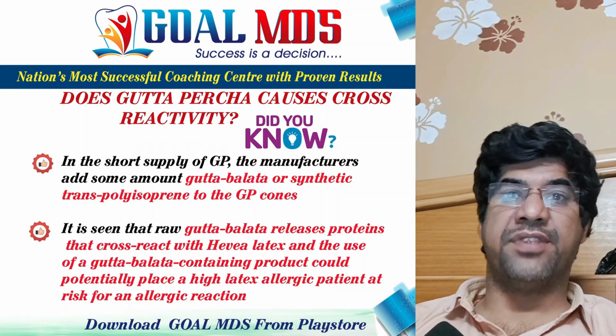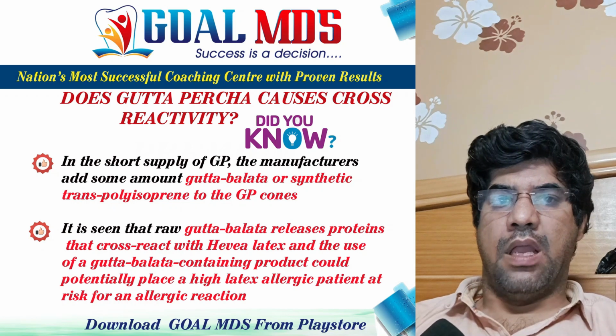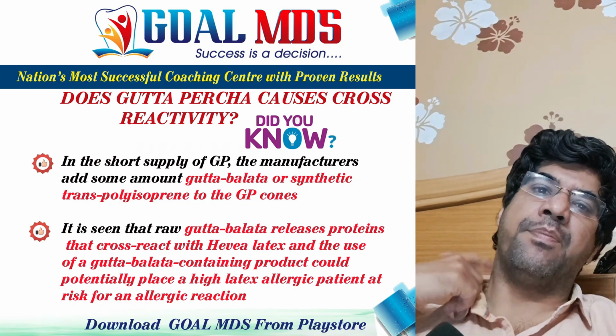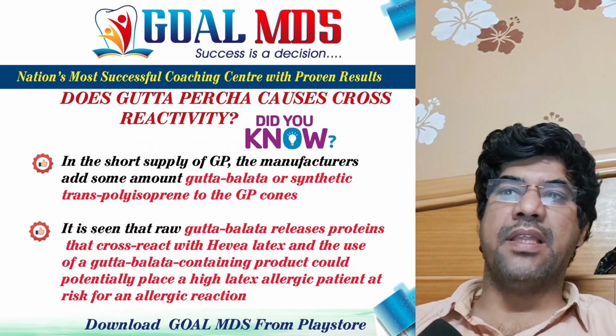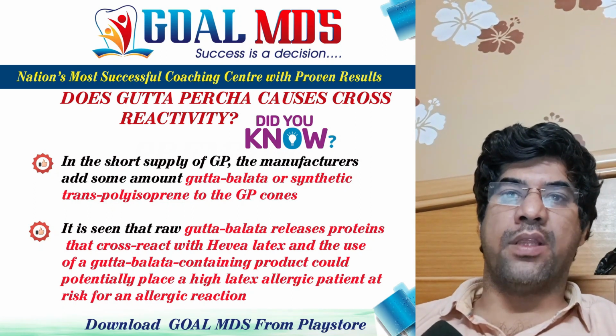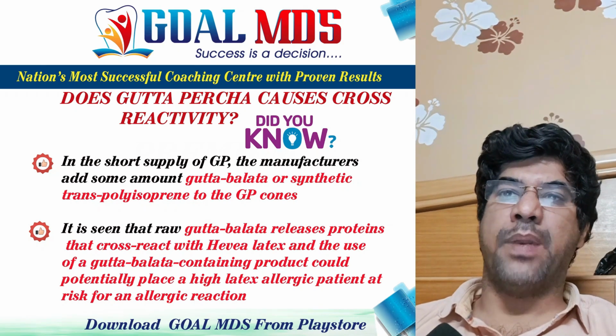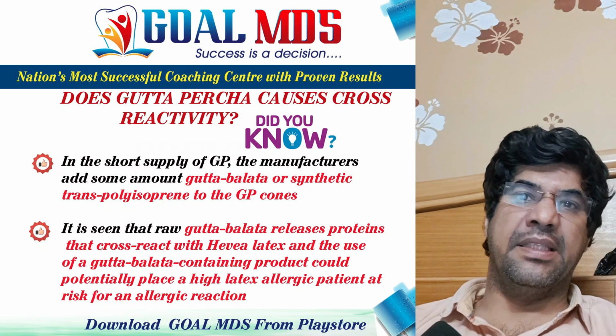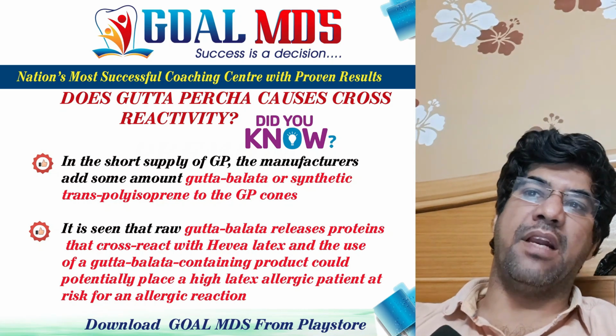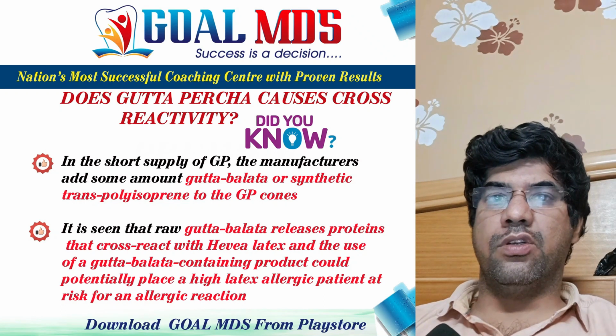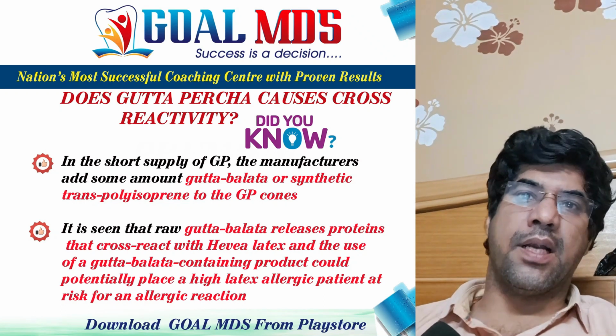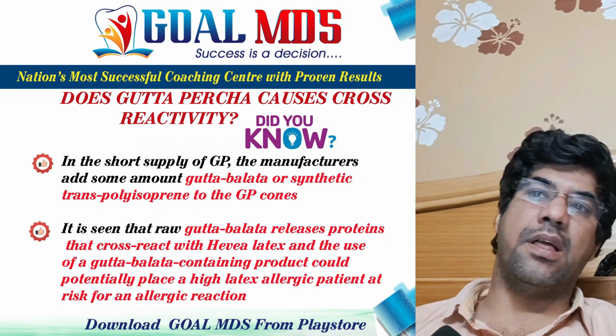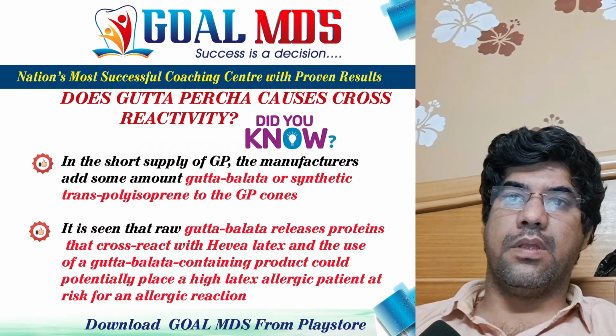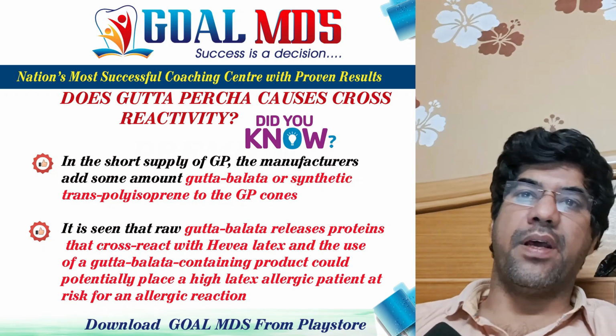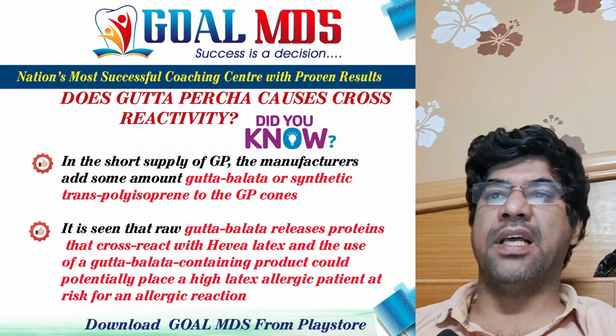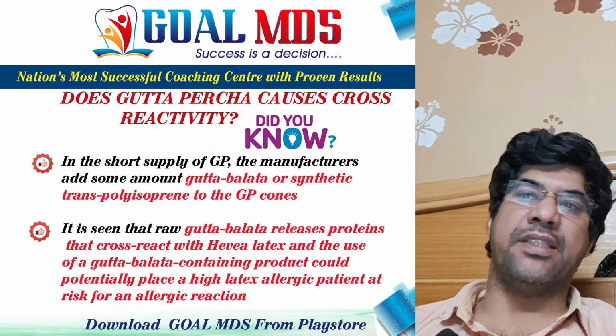Does gutta percha cause cross reactivity? In the short supply of gutta percha, manufacturers generally add gutta balata, or the synthetic trans polyisoprene, to the gutta percha cones. These gutta balata are derived from the same botanical family as the rubber tree. So the gutta balata will release the proteins. The use of gutta balata containing products could potentially place a high latex allergy patient at risk for the allergic reaction.